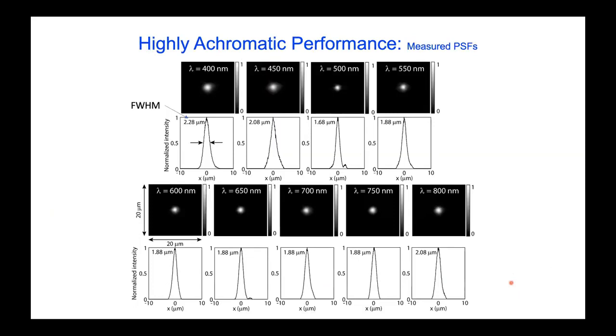And it works. It's quite achromatic. We were able to measure the focal spots as a function of wavelength, going all the way from 400 to 800 nanometers over almost a continuous spectrum. Here I'm showing 50 nanometer steps. We actually did this at even smaller steps, very small deviations.